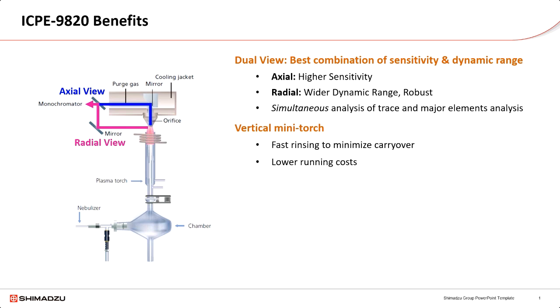axial view. The dual view provides the best combination of sensitivity and dynamic range for simultaneous analysis of trace and major elements. This is a key feature that benefits battery markets because for battery materials, we want to identify major elements like lithium, cobalt, nickel. But in the meantime, we want to analyze the elemental impurities like cadmium, lead, iron, copper that can negatively affect battery performance. The dual view allows you to run those unknown samples without extra sample prep, saving your time, increasing your productivity, and saving the operating cost.